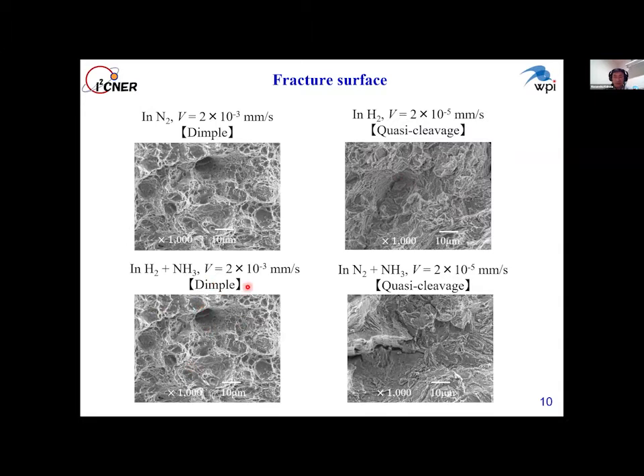So as you remember, in hydrogen plus ammonia with faster loading rate, the hydrogen embrittlement is mitigated. The fracture surface showed dimple. So we confirmed that ammonia prevented hydrogen uptake. And this fracture surface is obtained in nitrogen plus ammonia with lower loading rate. As you remember, J1C value was significantly lowered. In this case, the fracture surface shows quasi-cleavage. So this observation showed hydrogen embrittlement occurred in this environment in spite of the fact that the gas didn't contain hydrogen.